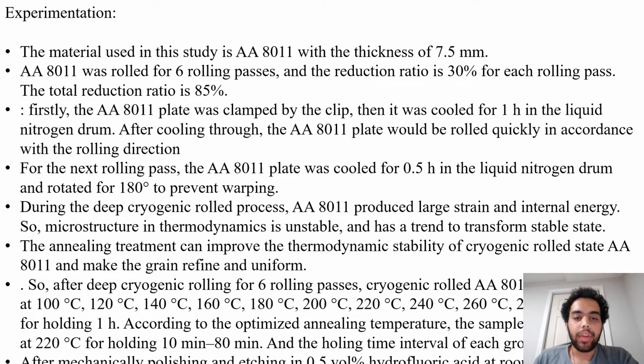During the deep cryogenic rolling process, aluminum produces large strain and internal energy, so the microstructure is thermodynamically unstable and tends to transform to a stable state. The annealing treatment can improve the thermodynamic stability of the cryogenic rolled aluminum and can make the grain refined and uniform. After cryogenic rolling of 6 passes, the rolled aluminum is annealed at many different temperatures, mentioned here: 100 degrees, 120, 140, 160, 180, and so on up to 260, 280, for about an hour. According to the optimized temperature, the sample holding time is between 10 minutes and 80 minutes. So this concludes the experimentation part.